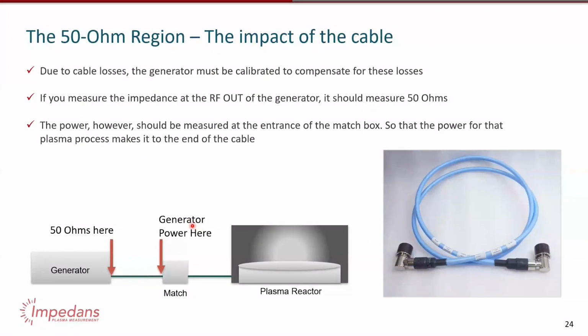So, for example, I mentioned that cables are an important part because you actually get power loss in the cable. So if you're in a fab where you have a generator in a sub fab and you have a matchbox on a different floor, you have a very long length of cable. And even if you calibrate your generator at the input, that's not what's reaching your matchbox. You could be losing up to 10% of your power into the cable, believe it or not, if the cable's a few meters long. So a general rule of thumb is, if you have a subfab, you should calibrate the generator power to the input of the match, but you should also make sure that the generator sees 50 ohms from its point of view to have the minimum reflected power.